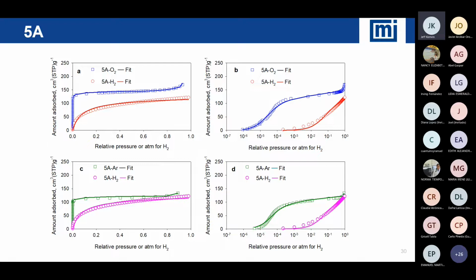We pick 5A because, again, it's in that size range that is very difficult for nitrogen adsorption. It's just out of reach for nitrogen. So if you start with 13X, you'll get very good nitrogen adsorption. If you move to 5A, it's very difficult. If you move to 4A, it's impossible to get nitrogen adsorption. So we started looking at different molecules, oxygen being a bit smaller, hydrogen, of course, being the smallest, and argon, because that's always the recommendation if it's usable for it.